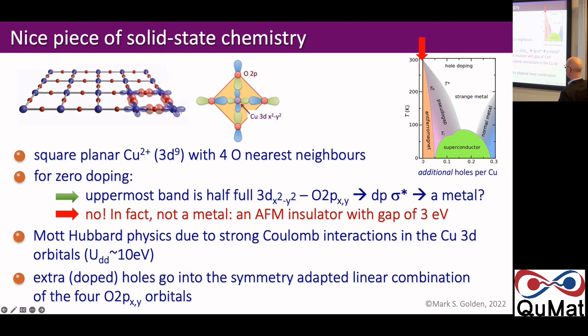Okay, so the extra doped holes, of course, don't go into this copper orbital because that would cost a whopping 10 eV to put another one in there. So they go into a symmetry adapted linear combination of these oxygen 2p orbitals. So the minimum model, really, if you want to start to think about this, is a three-band Hubbard model. It starts to get quite theoretically difficult.